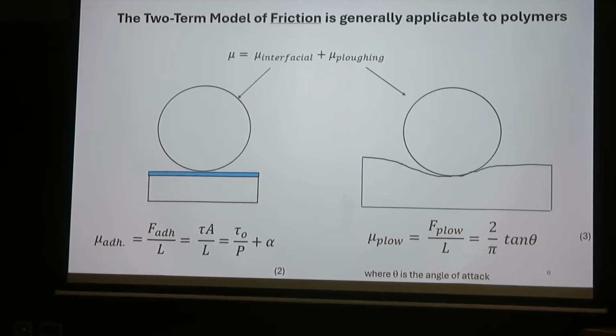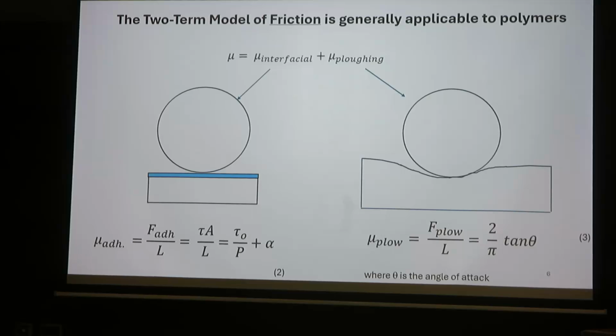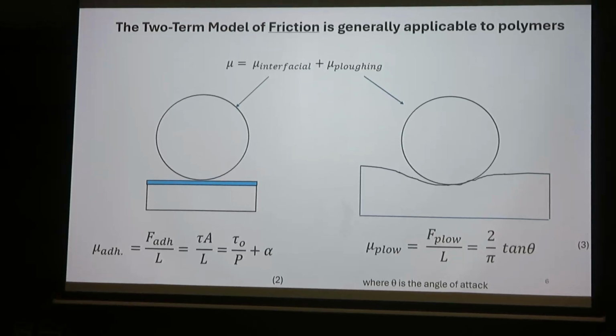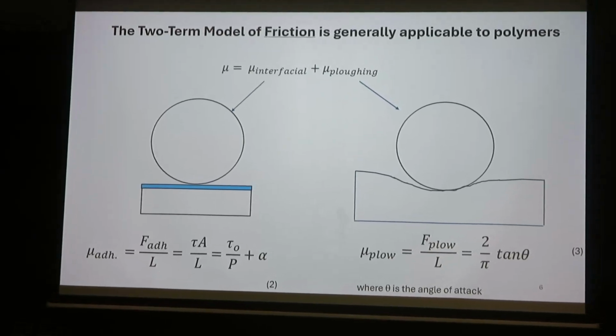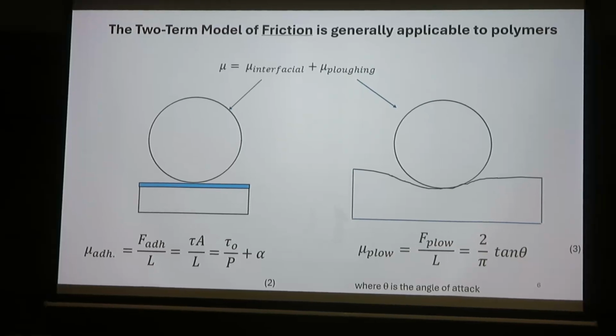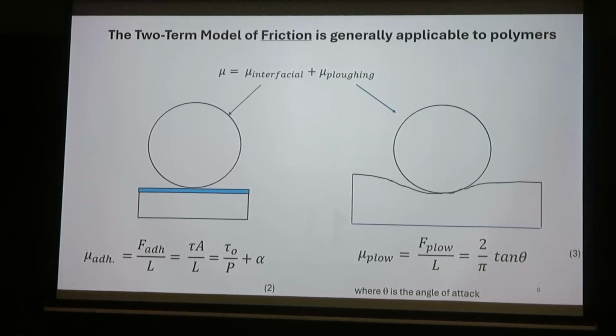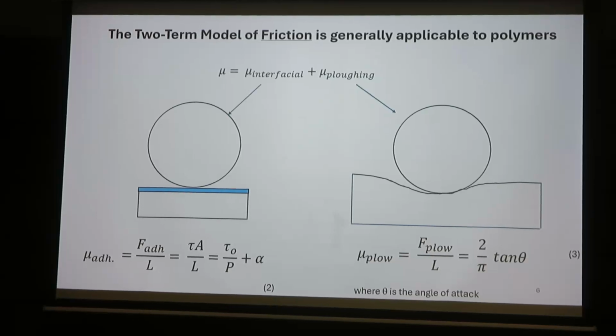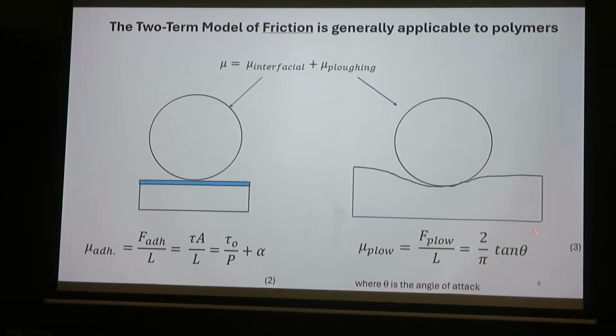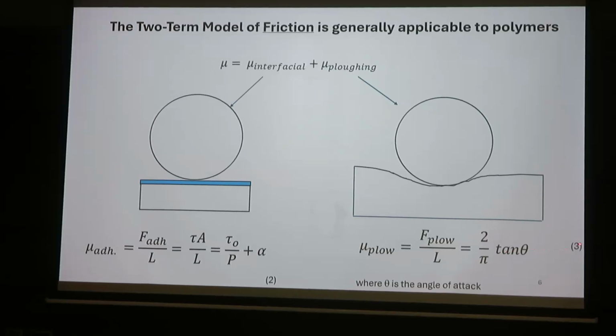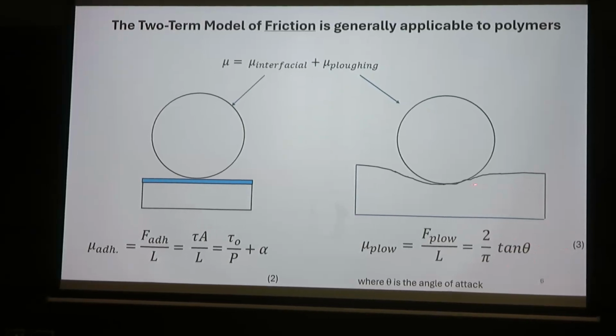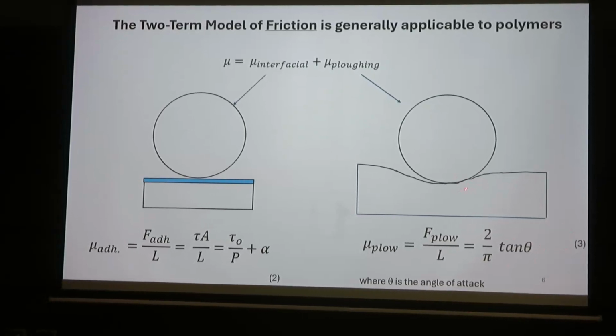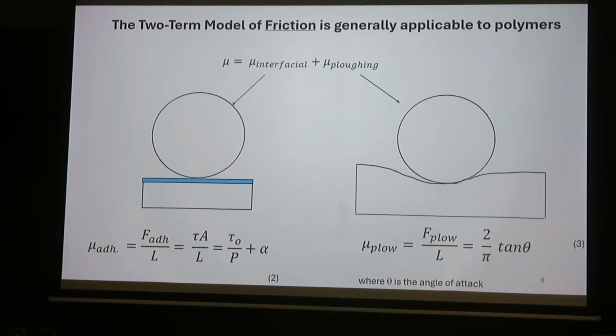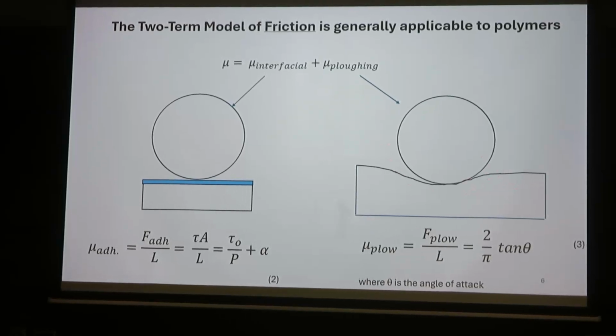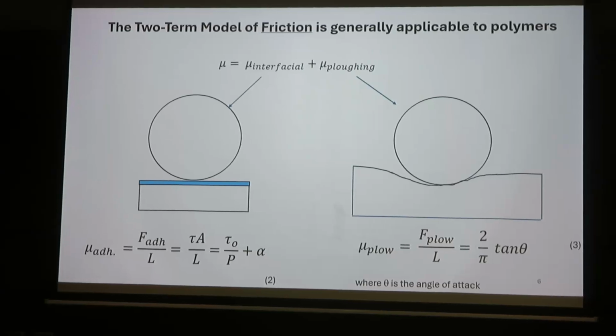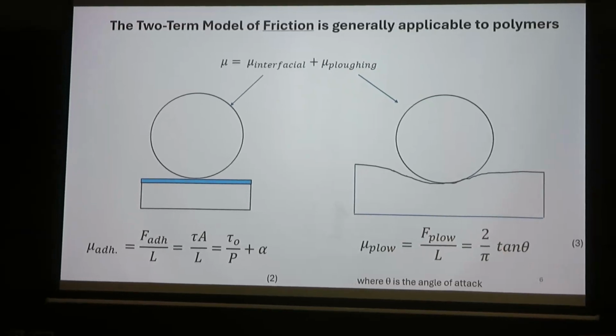And the second term is the plowing term. Plowing is basically not just the interface, but deep into the material. So that means the mechanical property might be very important for plowing, but theoretically plowing is given by this equation. The plowing coefficient of friction is given by this equation, where theta is basically the angle of attack, how sharp the asperity is. If we consider this as an asperity, what is the sharpness of the asperity? That is defined by theta.